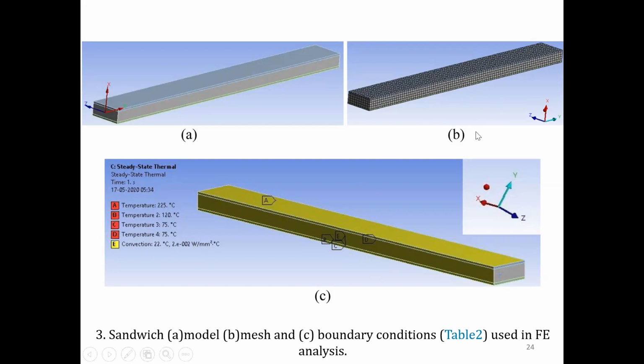Only the thrust was to just see a temperature and thermal stress distribution because of printing at higher temperature. So what we did, we carried out a three-dimensional steady state thermal analysis, and the temperature distribution is used as the load input. The temperature of printing has been fed for static structural analysis. We used a hex 20 element having an element size of 1 millimeters.